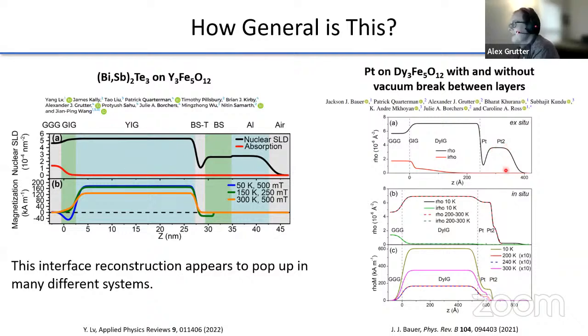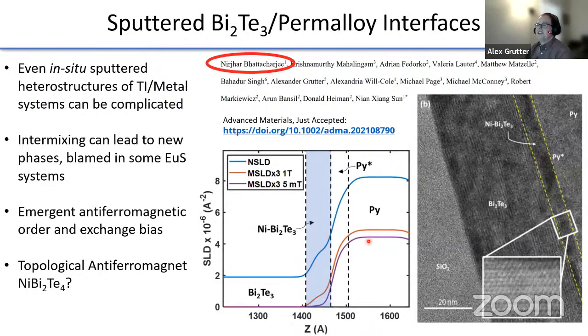On the other hand, if you grow the dysprosium iron garnet and then do an in situ growth of the platinum without any vacuum breaks, you get a really, really high quality interface. And this super strongly changes the coupling right at the interface. But that's not the only thing you need to worry about.